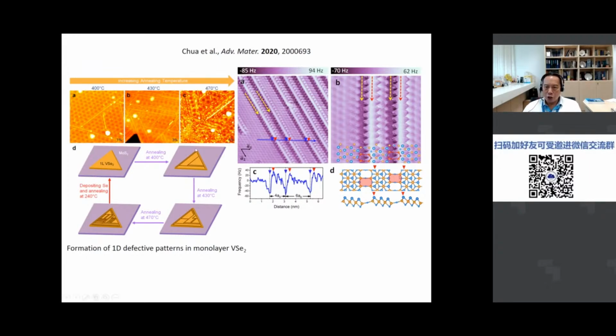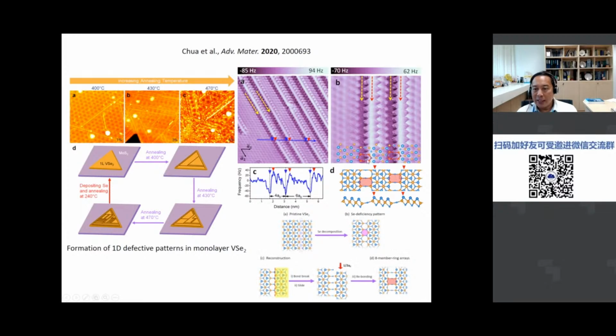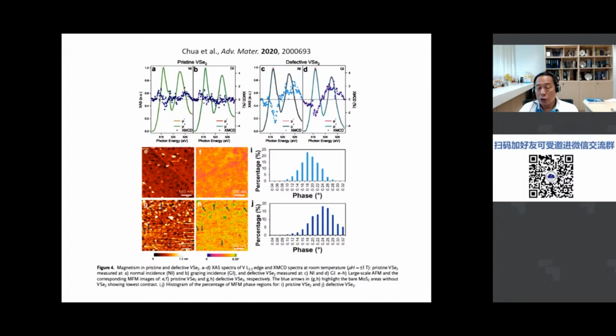And with high resolution AFM, we can see the topography of these line defects. Looking at these atomic resolution images, we can draw the structure of the vanadium diselenide, in particular the surface selenium structure, and we can construct this line defect, which is essentially a selenium deficient line defect. The reconstruction is formed by removing this defect and a displacement by half a unit cell. It gives this line defect. So we know we can form these line defects on the surface just by simply annealing the MBE grown VSe2. And we do the annealing in vacuum so that there's no oxygen around.